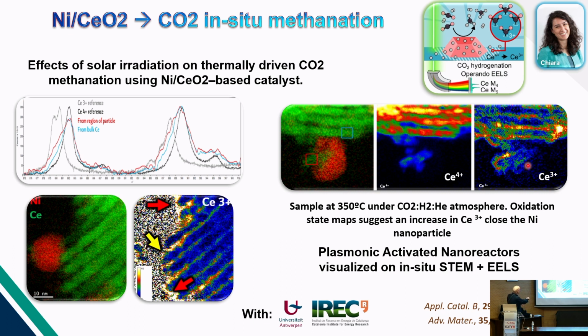So in these places is where the reduction happens, because you can control the oxidation state of ceria, for example, by doing electron energy loss spectroscopy. You see the difference of the peaks, and you can determine and map the oxidation state of your material. And like this, we could see the process in situ. So it's another way to demonstrate or to prove that your reaction is exactly what you were proposing.